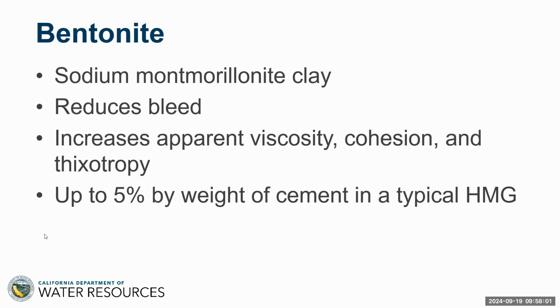So let's look at bentonite. Very misunderstood in terms of its properties and what its purpose really is. But the bentonite that we use is the sodium montmorillonite clay, not the calcium, sodium. It reduces bleed in the grout. So basically these particles, when they're hydrated, act as little parachutes for the cement and stop them settling. But it does increase apparent viscosity, cohesion, and thixotropy. Typically in our HMGs, we're adding up to about 5% by weight of cement in a typical high mobility grout.